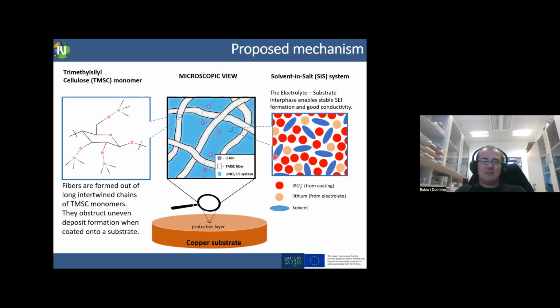But then with the salt inside, we worked with many different configurations of electrolytes, and we tried to understand why this conduction is working. And I need to mention already here that we don't see any dissolution of the nitrate. Of course, there should be some, but not in a detectable manner. So we propose that this interlayer works like a solvent in salt system. So it conducts lithium. It requires a solvent which can solvate nitrate. We can solvate nitrate, and then lithium is conducted through the nitrate elements.